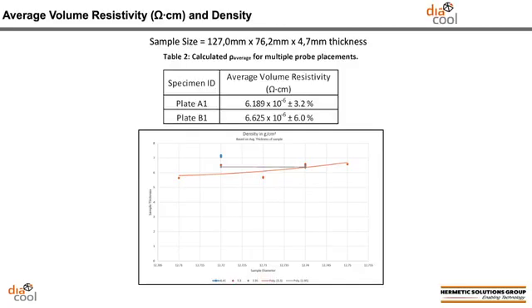So I wanted to test how electrically conductive this copper diamond Diacool product is. In the chart that you see in front of you at the top part of the slide, you'll see the volume resistivity measurements in ohms per centimeter, right around 6. This material is essentially 45% copper, so electrically it behaves very much like copper and is very uniform in conductivity in all directions.